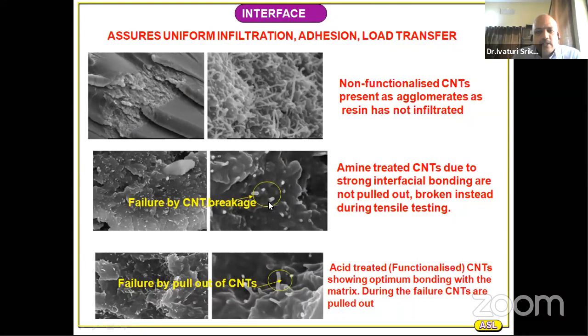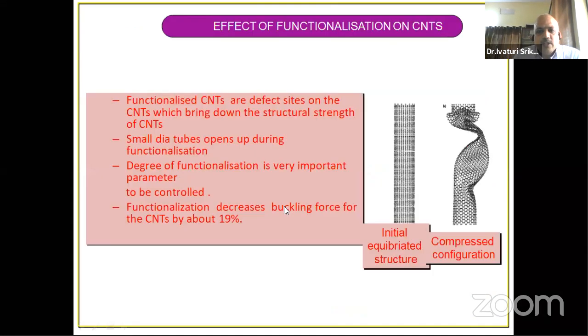So each of these areas, functionalization, dispersion, and purification of nanotubes, is again a vast ocean in itself, with various challenges and various kinds of possibilities. As I told, functionalization is essential, but as you are functionalizing it, you are creating defects. A stiff nanotube without any defect, you can see here. But when you functionalize it, all the defects will finally make the nanotube very poor. So the strength will come down drastically. So the degree of functionalization is very essential. You should introduce functional groups to such an extent that it doesn't damage the CNTs very significantly, but you tap its potential. So the degree of functionalization is one of the important criteria to use them as a reinforcement.